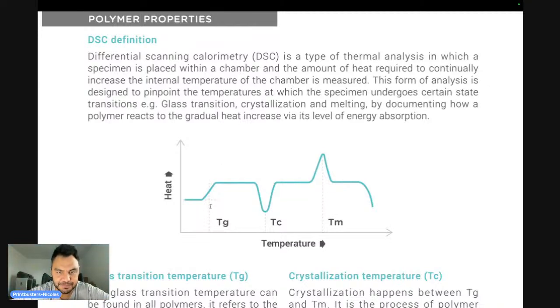So that's TG. And when it comes to a semi-crystalline, it's the same. When you reach TG, the amorphous region of the polymer will also soften, but all the crystals around it will maintain the overall structure because the crystals are not going to soften. Okay, what is the TC? The TC is the crystallization temperature. It's not really the temperature at which you can form the crystal, it's the temperature at which the crystal will form the fastest.